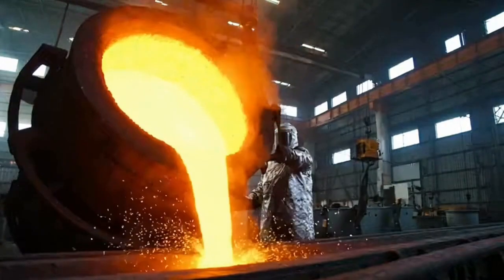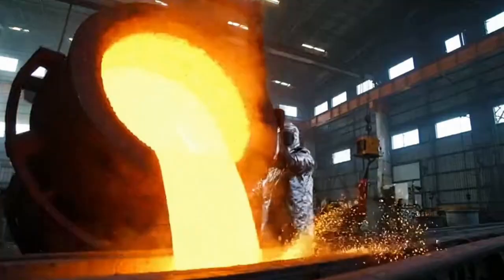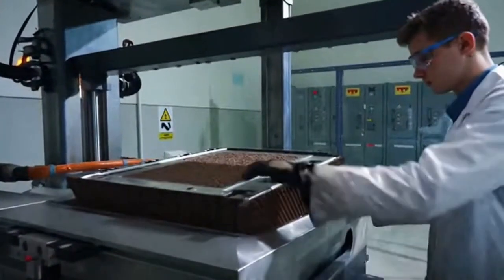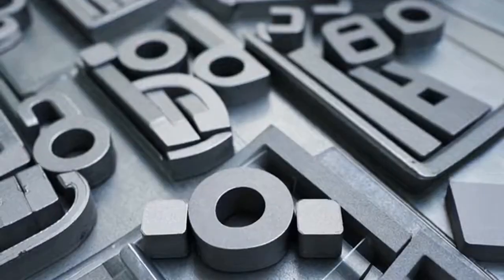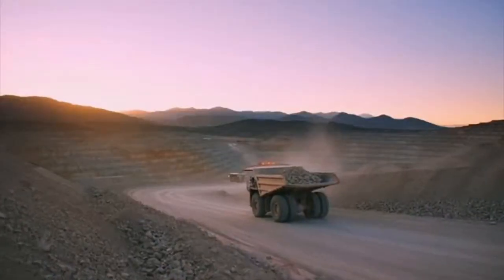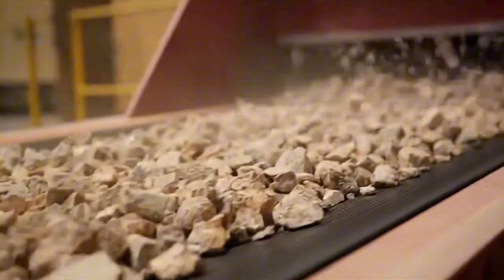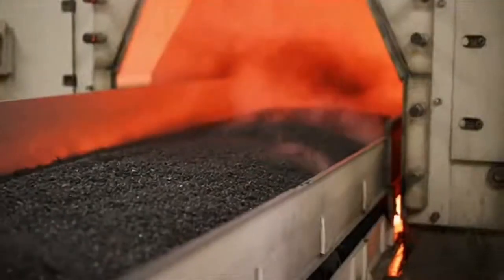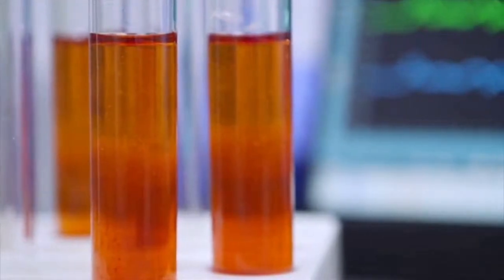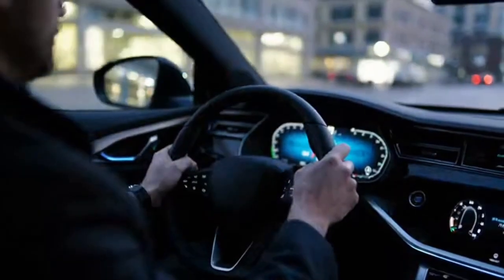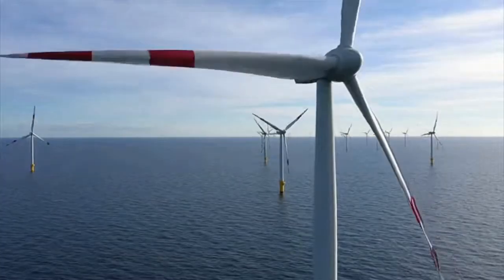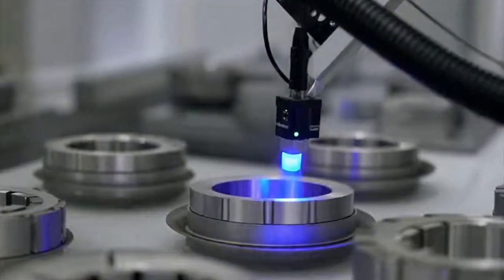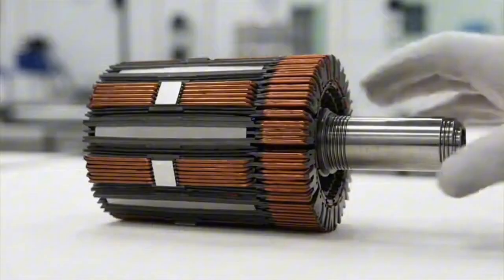That solution is a who's who of the rare earth family, all the light rare earths like cerium, lanthanum, praseodymium, neodymium, plus a bit of samarium, europium, gadolinium and maybe some heavies if the ore had any, all jumbled together. At this stage, it's as much a triumph of logistics as chemistry to handle it. Next comes the solvent extraction hall, where with a combination of kerosene-based solvents, extractant molecules, and a precisely orchestrated waltz of mixing and settling, you separate that family of elements one tiny step at a time.